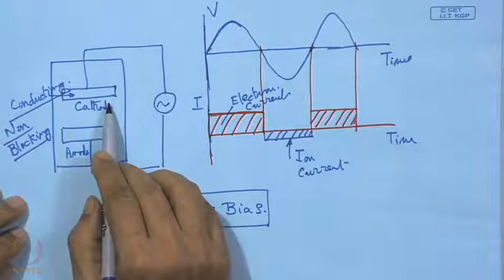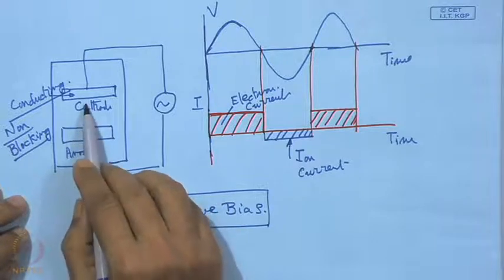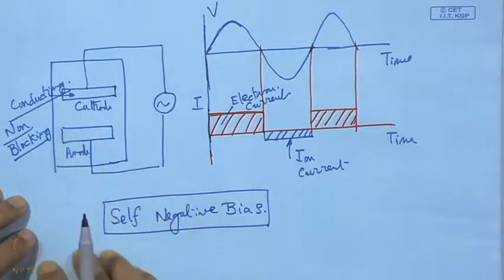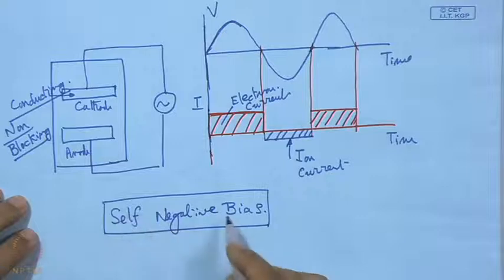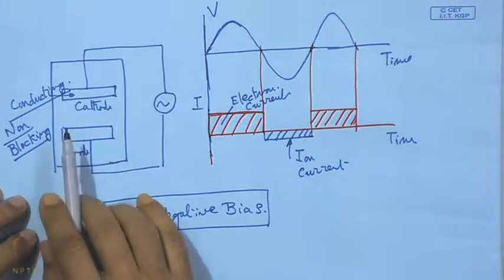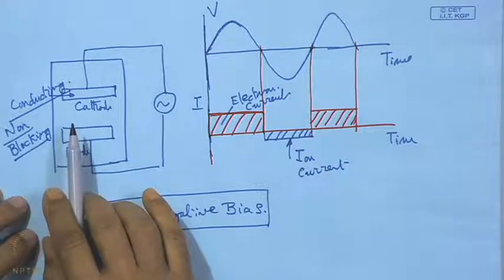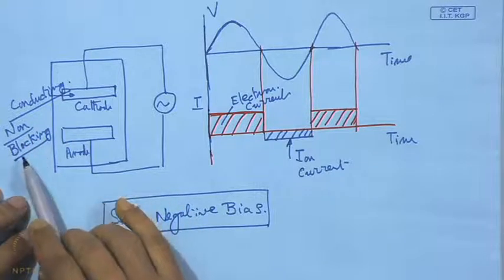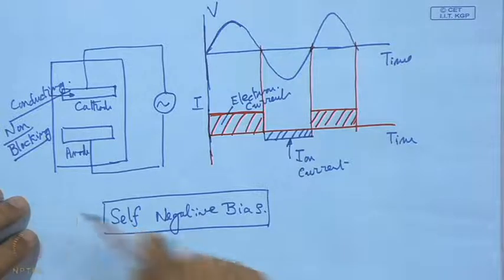So, on this cathode surface, a self negative bias voltage must develop. Why? This is necessary to pull the ions which will do the necessary dislodgement, ejection of the sputtered material from this cathode surface, and in addition secondary electron also from that cathode surface. So, self bias is anyway a must for sustaining the discharge to carry forward this sputtering process.